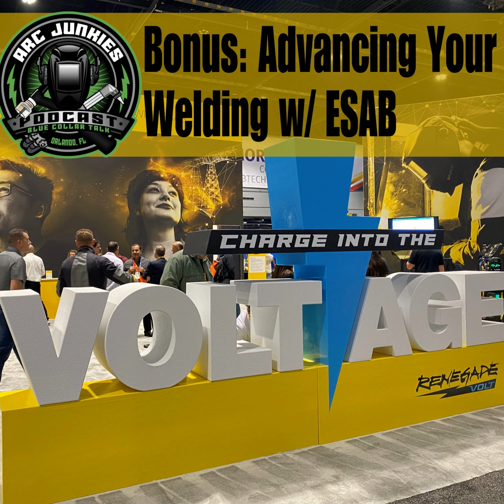Yeah, and what we're finding is that there's also a little less dilution with the base metal. With the wire, we can control the chemistry a lot better than we can the plate chemistry. So with the increased travel speed and the increased deposition rate, we have less dilution with the base metal. We have better mechanical properties at the end of the day. So we found, and I guess at the beginning we were looking into it and we're like, wow, why? With these wire combinations, we're getting great mechanical properties, great Charpys, so it's a win-win.